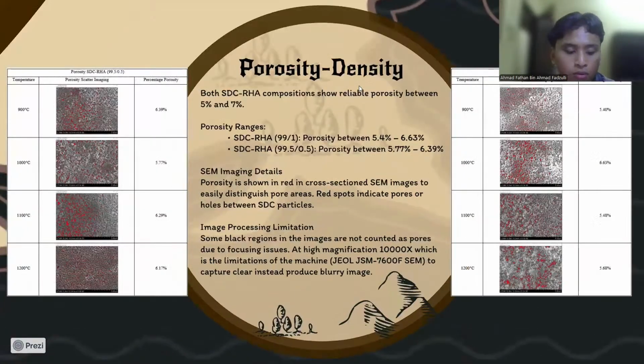Okay, let's jump to porosity density. Both SDCRHA compositions show reliable porosity between 5% and 7%. Porosity range, as you can see: 99% SDC porosity is between 5.4 to 6.63%, and 99.5% SDC porosity is between 5.77 to 6.39%.